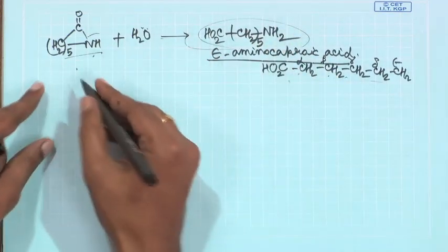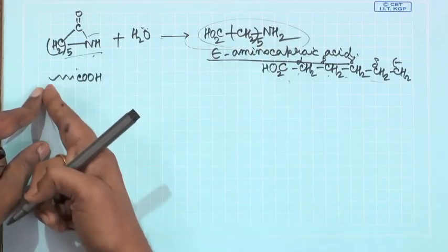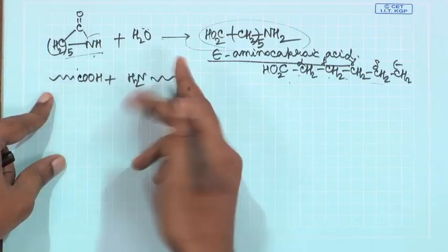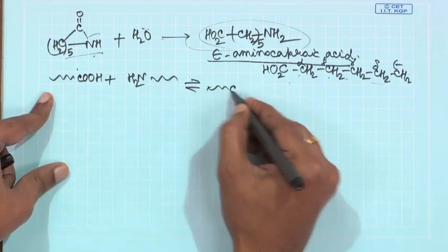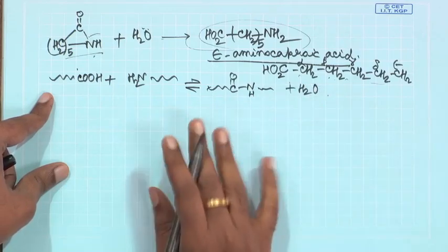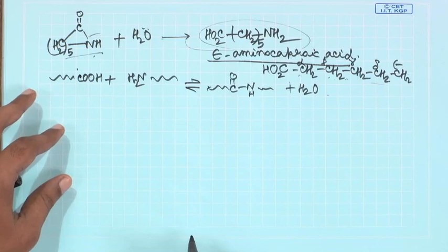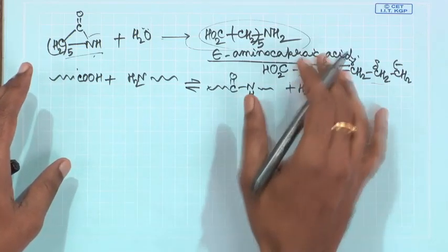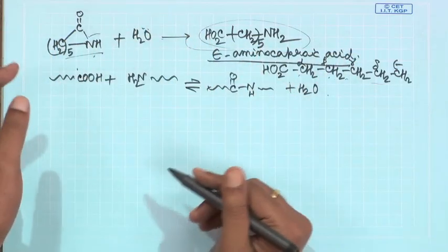So, self amidation, so self polymerization, let us say at the end of a growing chain you have CO2H, it can react with an NH2 at the end of another growing chain, just a generic way, in a reversible way, and it can produce your polymer. That can happen. Or what can happen is that this particular amino acid can initiate the ring opening polymerization of lactam.